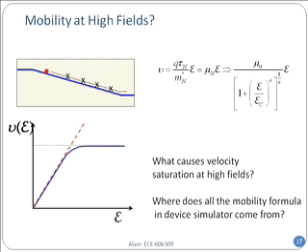And that number, called saturation velocity, is on the order of 10 to the power 7 centimeters per second, almost for all materials. That's why changing silicon to gallium arsenide in modern technology may not always help very much. The thing is that this saturation velocity is a number which is almost independent of material. We'll explain where it is coming from.